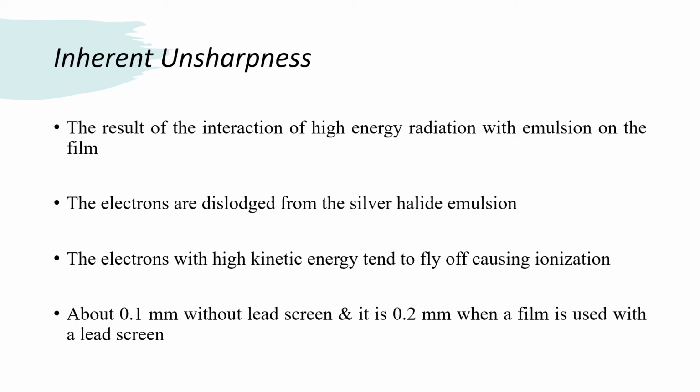The inherent unsharpness value is about 0.1 millimeter without lead screen, and it is 0.2 millimeter when the film is used with the lead screen. So without lead screen it is 0.1 millimeter, and with lead screen it is 0.2 millimeter.